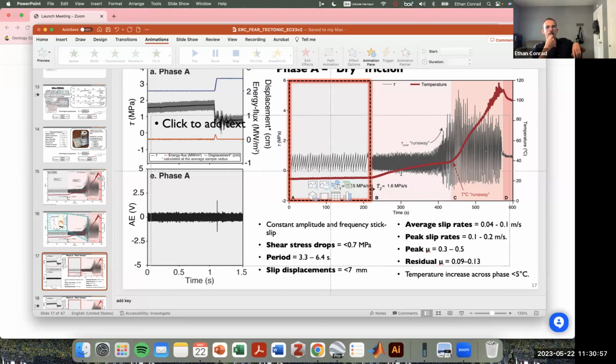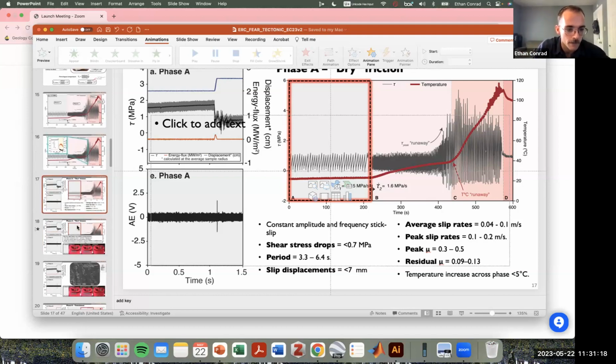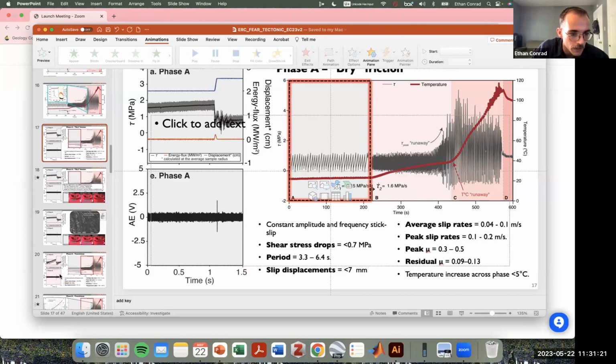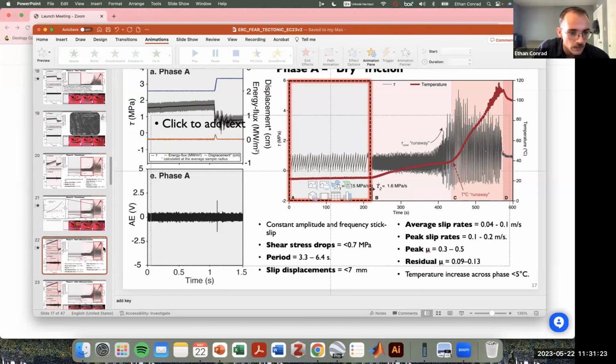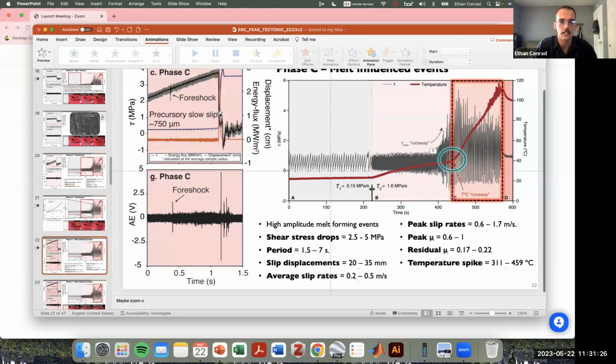I think you could call it an artifact. It holds information physically. It's like the sample assembly is spinning so fast that this is the recoil response, and so it stops, and then the machine recoils, and so we actually see in the displacement curve here. Let's go to the phase C event. In the phase C event here, we see that recoil. So the whole thing is reversing because it's overshot, essentially, the amount of rotation.